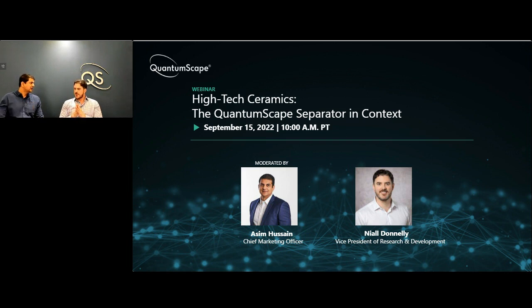Discharge is basically the reverse process. So you have got lithium on your anode, and now you want to discharge. What you need is for the lithium to leave the metallic lithium and enter into your separator, move through the separator, and then go back to the cathode. And again, it's the exact reverse process of the deposition. This is called lithium stripping, and you basically start taking lithium from the metallic anode, and it converts from lithium metal, it gets ionized to a lithium ion, and it enters your ceramic separator and starts to move back towards the cathode for discharge.